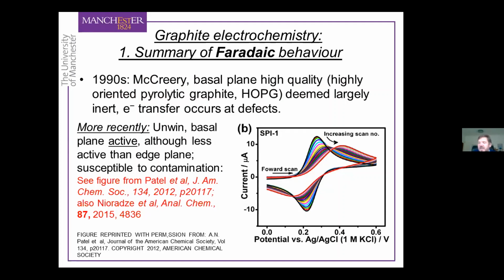And just to summarize the conclusions of his work, he deemed that the basal plane of graphite was actually inert with respect to electron transfer. And the reason that you saw electron transfer on basal plane graphite was because even high quality samples will be defective to some extent. They'll have some sp3 sites or atomic vacancies and so on and so forth. And he concluded that it's these defects that were responsible for the electroactivity of the graphite. Then more recently, this area was revisited by Pat Unwin's group, and they came to basically the opposite conclusion. They concluded that the basal plane of graphite was actually active. And then there was a debate about the relative activity of the basal plane versus the edge plane. And I think now the consensus is that it is less active than the edge plane.